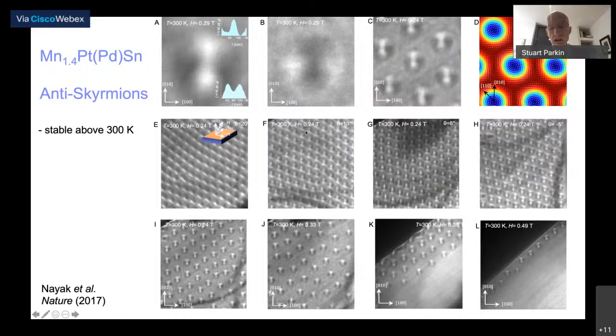And it turns out then that the rest of this image shows you that these anti-skyrmions form arrays depending upon the temperature and the vertical magnetic field. As we increase the out-of-plane magnetic field, eventually they will disappear as all the magnetization in the structure is oriented parallel to one another.